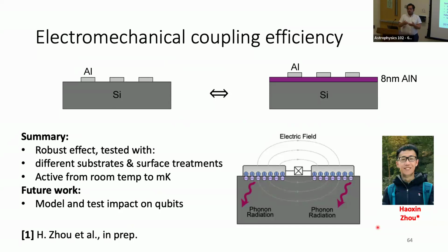We repeated this with multiple surface preparations. It's a pretty robust effect. It shows up in p-type, it shows up in intrinsic, it shows up with oxides at surfaces, and so on. We see the signal all the time. So now we're trying to more carefully calibrate it and put a number on how much of a loss mechanism this would constitute for qubits. The numbers are currently from 10 hertz to the kilohertz range, depending on the mode matching you have between the two systems.